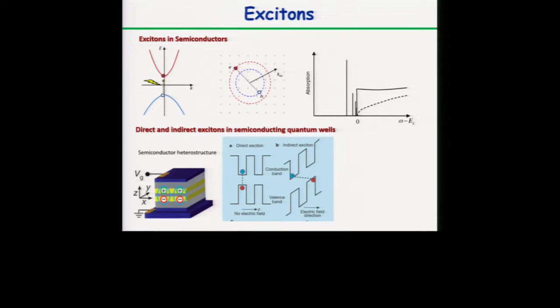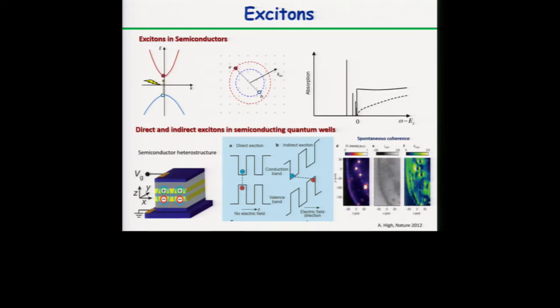And if we separate them in space, so if we have 2 layers separated by an insulator in between, we can have electrons and holes in different layers, and that is what is called an indirect or interlayer exciton. The advantage of having an interlayer exciton is that the lifetime is dramatically increased, because now the wave function is separated by an insulator. That has been proven for gallium arsenide, where they were able even to prove spontaneous coherence or Bose-Einstein condensates, but this is all at very low temperature.